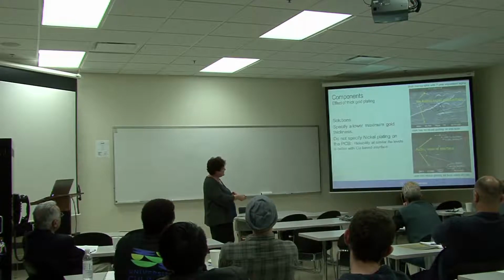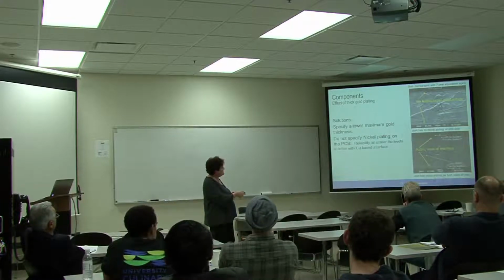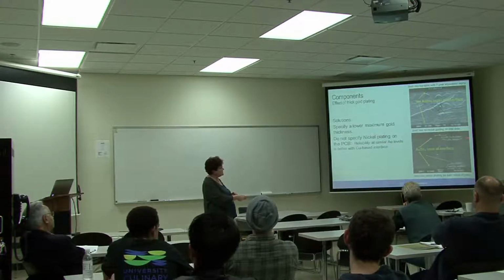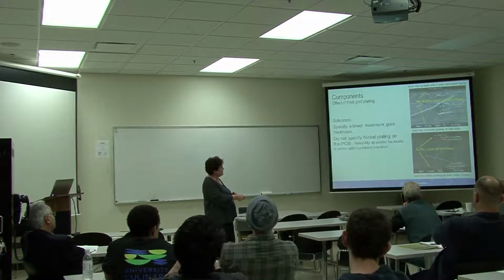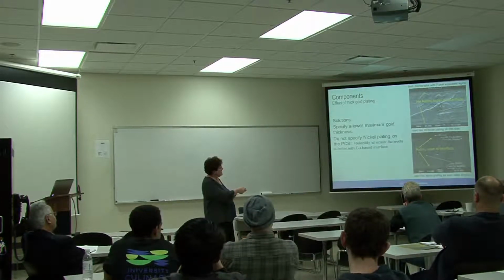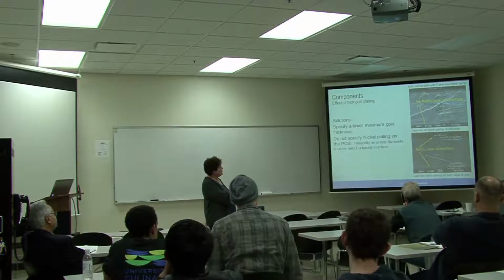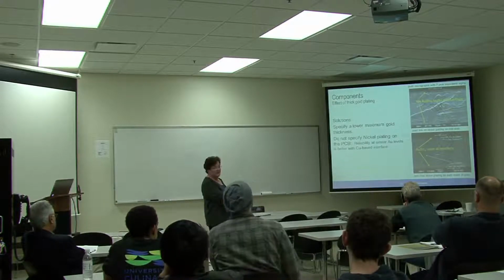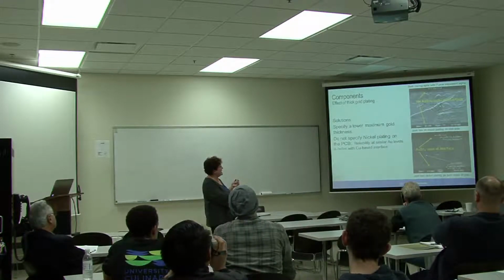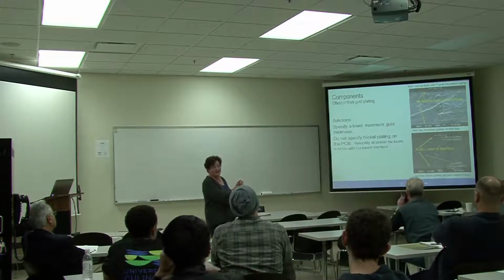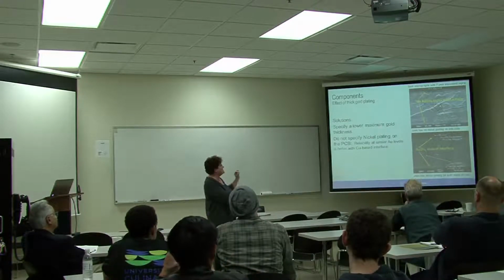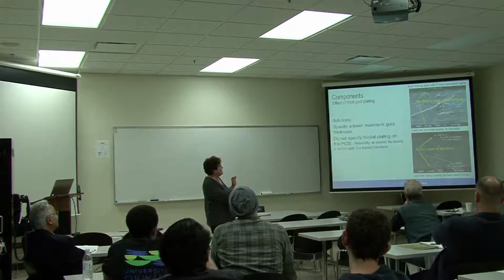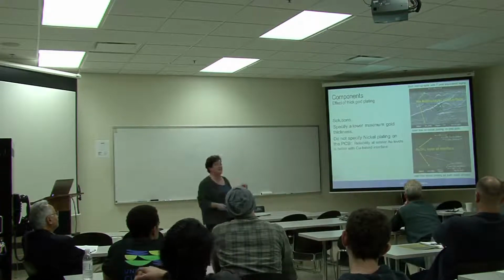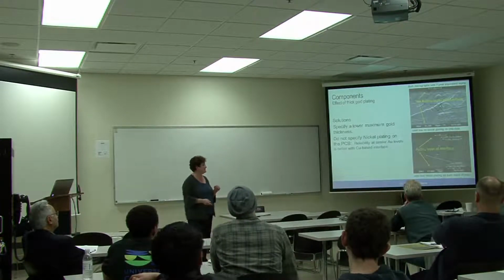So this one is an aged sample with the same amount of gold as this one, but with nickel on both sides, no copper available. And you have that gold tin layer at the interface. And then on this one, the gold tin layer didn't form. It's Cu6Sn5, the copper tin intermetallic. And there's an awful lot of gold all the way through the joint, so that's not good. If you get too much, it's still bad, but you still don't end up with as high of a chance of that failing.